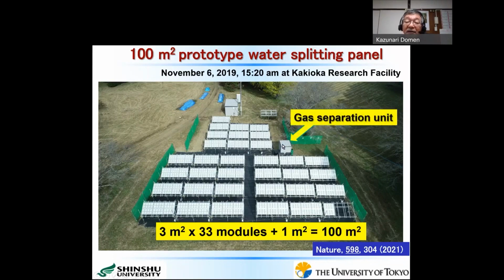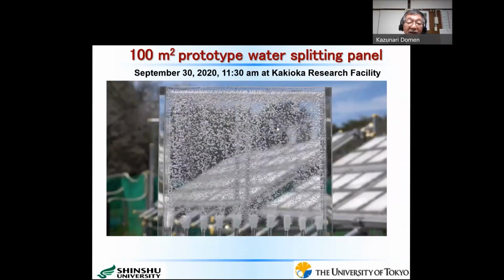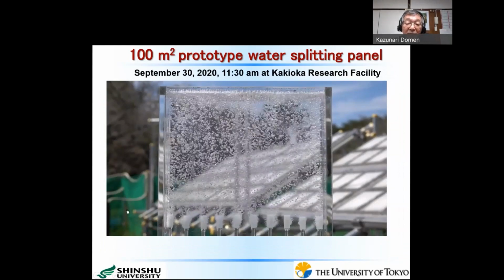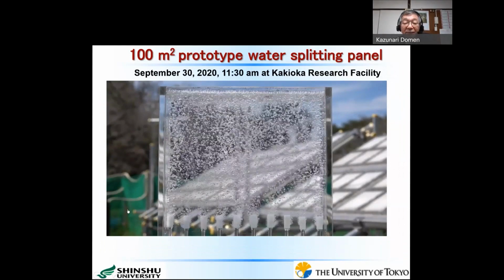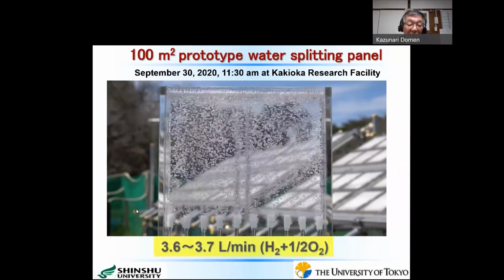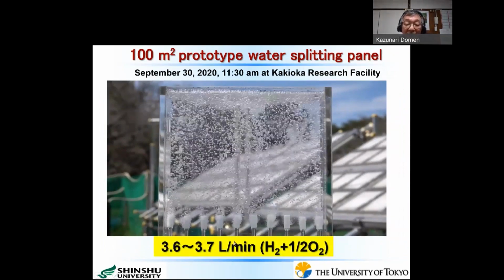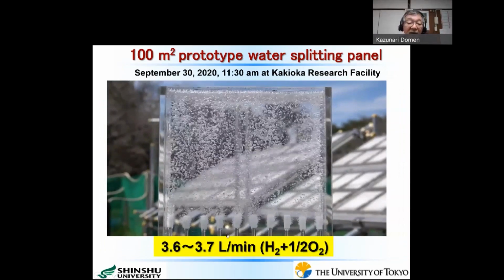In addition to that, here we have a gas separation unit. Actually, this work was supported by NEDO funding agency of METI. And this is the first example of the pilot scale solar hydrogen production system using photocatalyst. And this is an example of the evolving hydrogen and oxygen gases before introducing into the gas separation unit. In this particular case, about 3.6 to 3.7 liter per minute of hydrogen and oxygen gases are evolving.